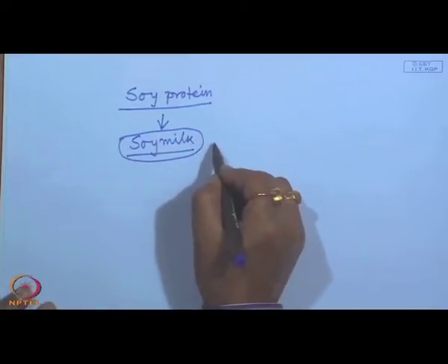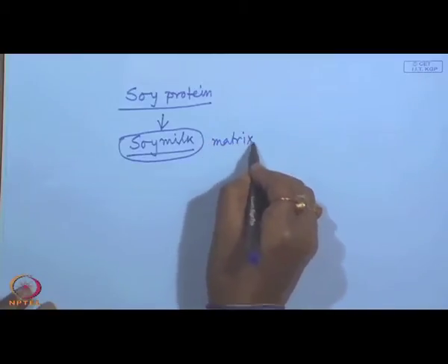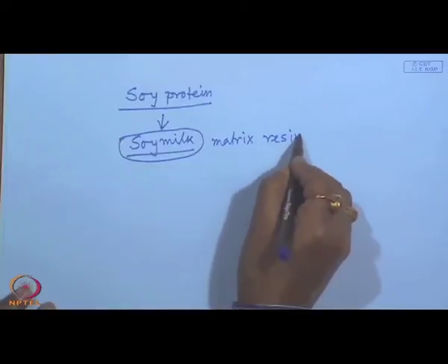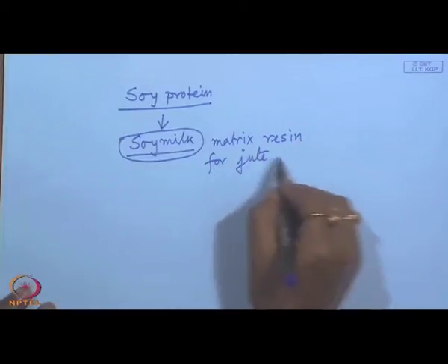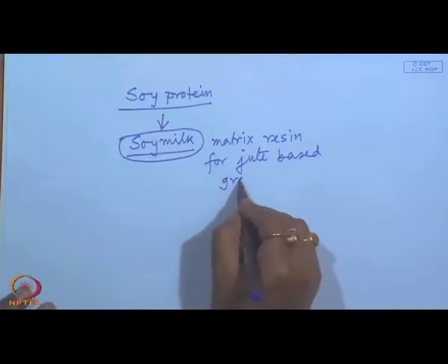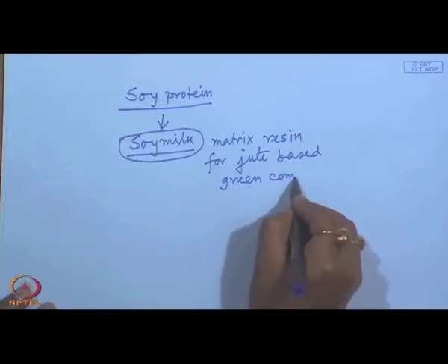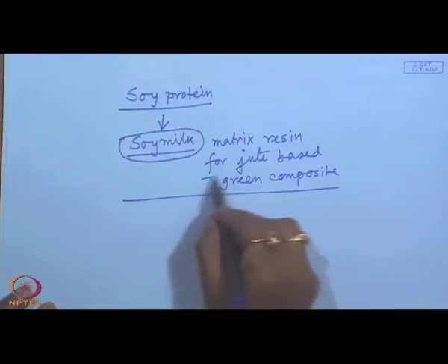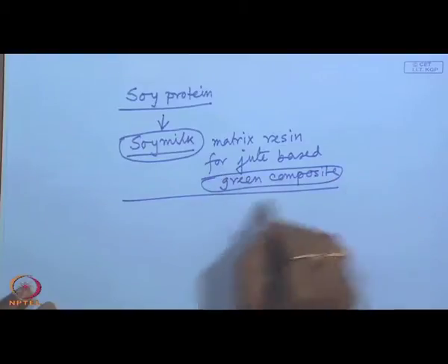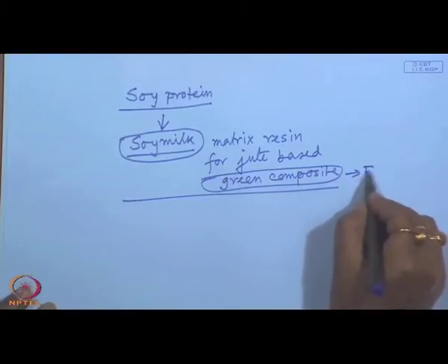In fact, we have used this soy milk as a matrix resin for jute based green composite, and we have found this green composite as fully biodegradable.